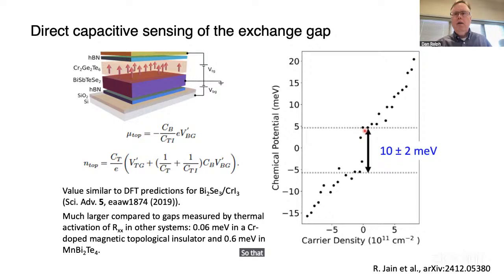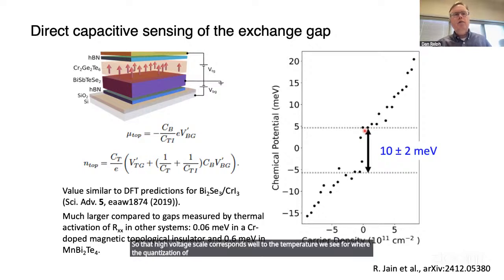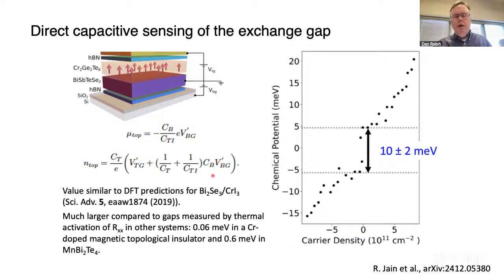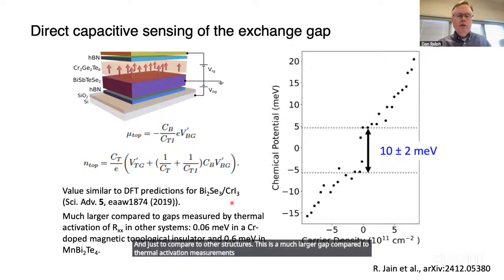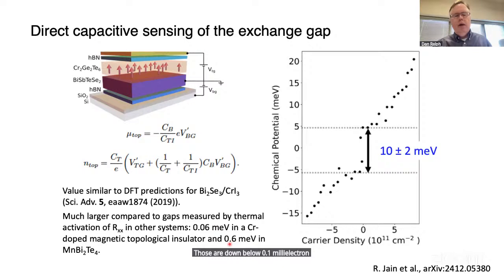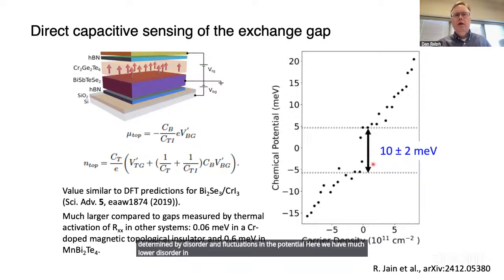That large energy scale corresponds well to the temperature we see for where the quantization of the Hall conductivity remains. And just to compare to other structures, this is a much larger gap compared to thermal activation measurements of the longitudinal conductance in magnetically doped systems. Those are down below 0.1 millielectron volts. And even for manganese bismuth telluride, those kinds of measurements are down below 1 millielectron volt. And I think what's going on with that comparison is these are just really measuring different quantities. In those systems, those gaps are really determined by disorder and fluctuations in the potential. Here, we have much lower disorder in these pristine states. So we really do have more of a direct measurement of what the exchange gap looks like.